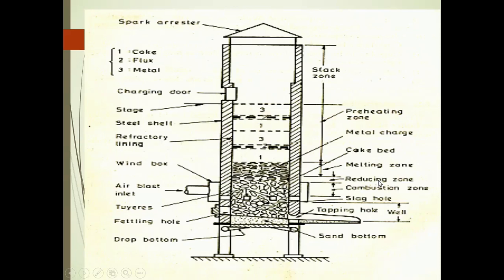and it is also called as a carburizing zone because carbon which is present in the coke, that carbon reacts with the carbon dioxide and it is forming twice CO, that is CO2 plus C, that gives 2CO. CO means carbon monoxide. Carbon dioxide is reduced to the carbon monoxide in this zone. That's why this zone is called as a reducing zone. Or carburizing zone means carbon is absorbed by the molten metal inside this zone and unnecessarily brittleness of the material increases. That's why this zone is called as a carburizing zone.